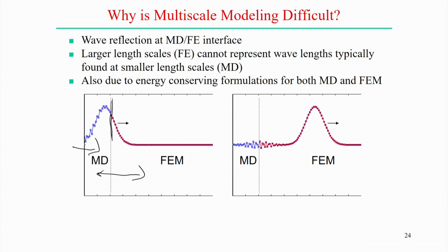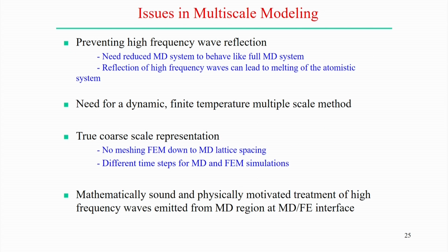Also, an energy conserving formula for both molecular dynamics and the finite element method is really difficult at the interface: how to conserve the energy when we try to link these two scales, the molecular dynamics and the finite element. So these are the typical issues. Now, in general, preventing high frequency wave reflection needs reducing the molecular dynamic system so that it behaves like a full molecular dynamic system. Reflection of the high frequency waves can lead to the melting of the atomistic system. So we should be very careful in linking how we can reduce the molecular dynamic system to behave like the full molecular dynamic system.